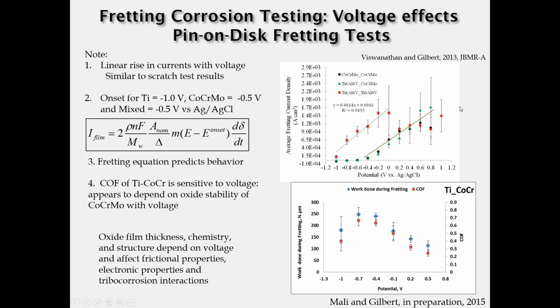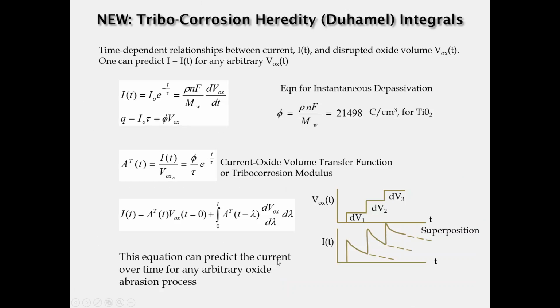When you look at the voltage-dependent effect of these pin-on-disc measurements, I would just want to point out on these curves that you see the same kind of linear dependence of the fretting currents with potential that you saw in the single asperity scratch test. So again, the voltage of the interface, or across the interface, is very important for the behavior of this system. In addition, the frictional interactions of the interface can be highly dependent on that potential as well, as is shown here.